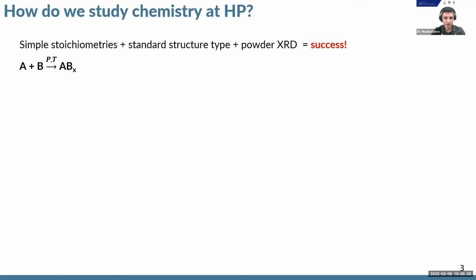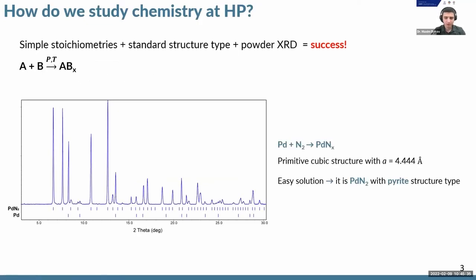Historically, we use powder X-ray diffraction to do that. And this works really very well when we have simple chemical reactions, formation of binary compounds, for example, with simple stoichiometries and standard structure types. We always like to see a diffraction pattern like this, which is very clean without any additional products, as in this example of the synthesis of palladium N2. The diffraction pattern can be easily indexed with a cubic primitive unit cell, and one can perform real Rietveld refinement with the determination of atomic coordinates, not just profile fitting, to solve and define the crystal structure.